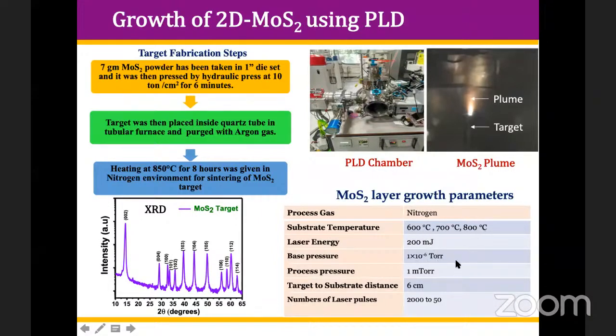Laser energy is there, base pressure. Better the vacuum, less the defects are there in the systems. Then the processing or growth pressure, 1 millitorr by using the nitrogen ambient.